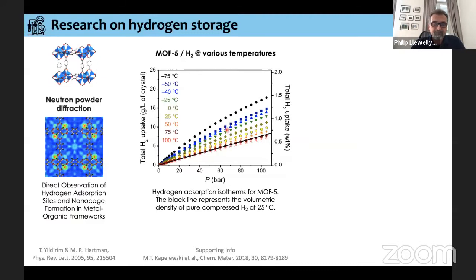We could then wonder, what are the adsorption mechanisms? What we see down here on the left-hand side is the direct observation of hydrogen in MOF5, and we can see that these red points and these green points show that hydrogen would like to migrate towards these metal centers. We can see the metal centers here in this MOF5. A fair bit of the pore space has much less density than close to the metal side. So this gives us a first idea of how we could improve the materials for the adsorption of hydrogen.